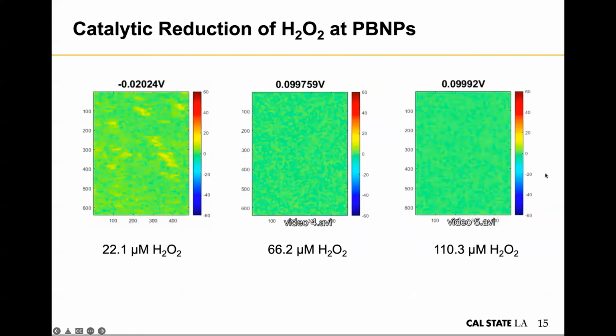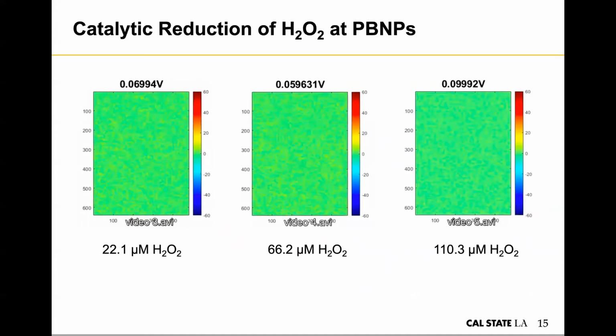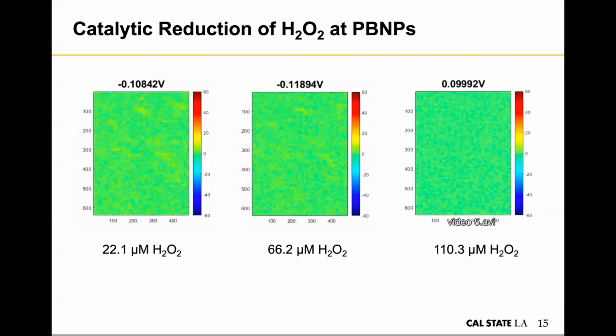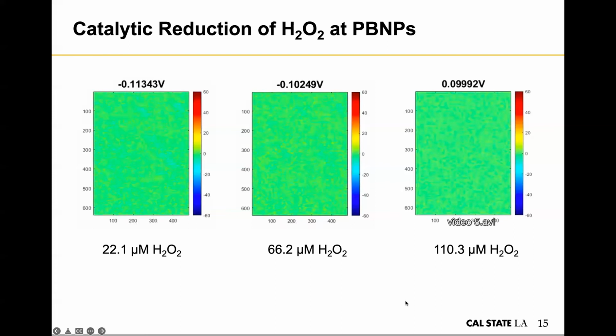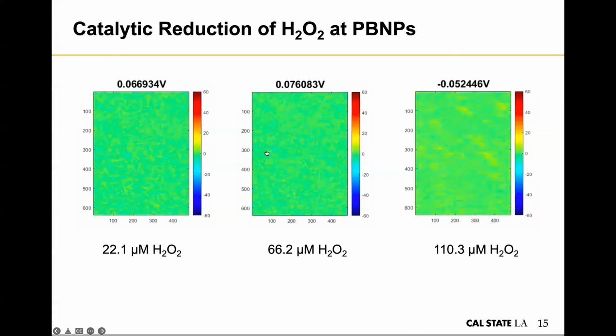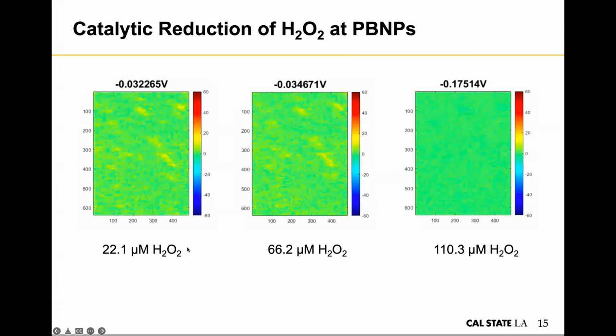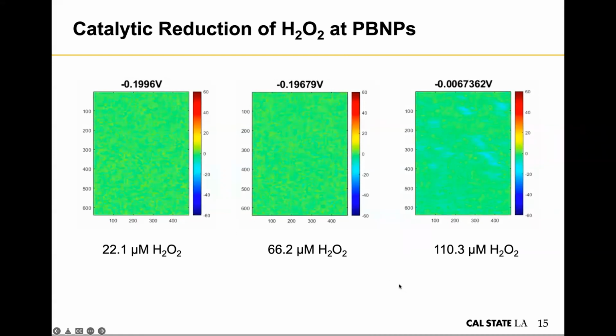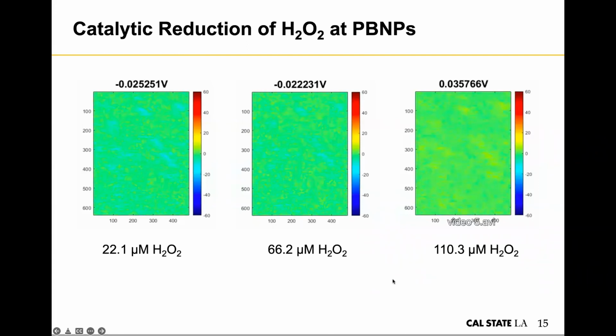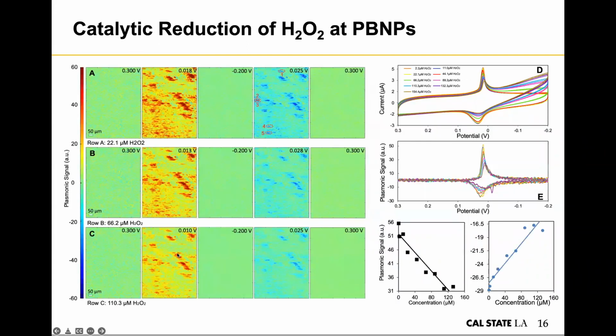And then finally, we also did some hydrogen peroxide reduction with those Prussian blue nanoparticles, trying to see whether we have hydrogen peroxide sensing capability at the individual nanoparticle level. Here I'm showing you the videos of the Prussian blue reactions at different concentrations of hydrogen peroxide. It might not be very straightforward with the videos, but if we overlay the images together at different concentrations, you might notice that there is a change in intensity when the concentration of hydrogen peroxide is different.